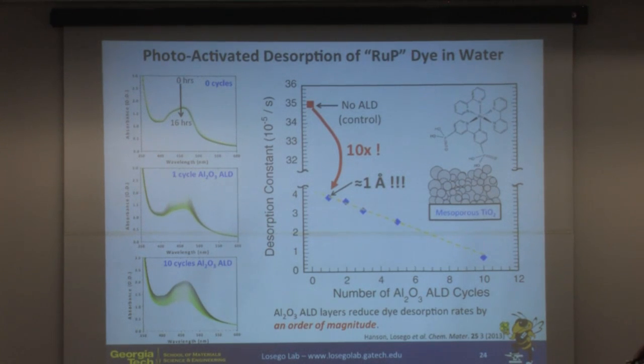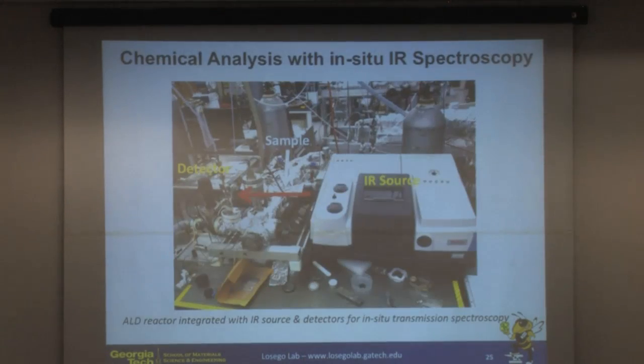So we've gone a bit further to look at, again, if we expose this to light. So this was Ken ran these experiments now, where as he had done before, when we exposed these to light, we saw even faster detachment of these molecules. So without a coating, if we can plot the desorption constant for these materials, we see that as we add this alumina coating, even just one angstrom, one cycle of this material, we can improve the attachment by about an order of magnitude in terms of decreasing the desorption coefficient for these molecules.